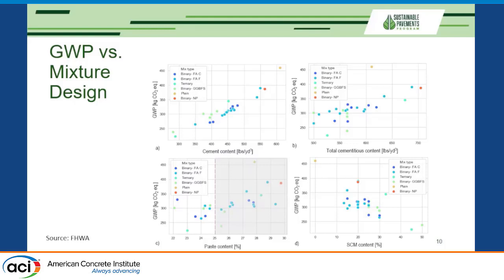Also, different mixes in terms of whether they are binary, ternary, what type of SCM you have, they will also fall on different parts of this line, but in general, higher cement content, higher global warming potential, no question about that. When we compare total cementitious content or even total paste content with GWP, we also have positive correlation. It's just not as strong because not all of our powder material combinations, of all of our pastes, are the same. And here again, you can see this limit of 25% paste content prescribed by AASHTO PP84, and all of our mixes that have paste content above it. You can see pretty high GWP values.